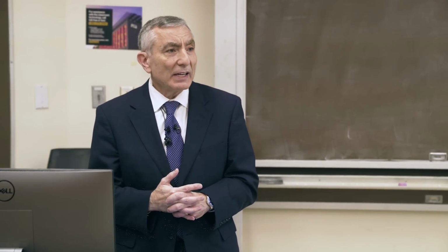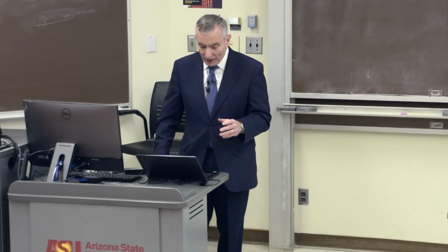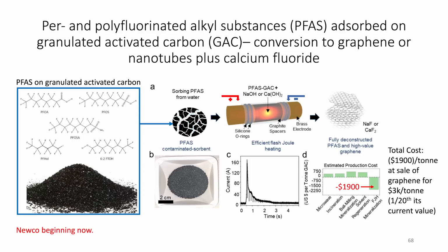You can get PFAS out of water fairly well by using a carbon filter. Carbon works actually quite well. And you can remove the vast majority of these water-soluble PFAS compounds from water. So here's what the PFAS compounds look like. You use activated carbon. So what do you do with the activated carbon now that it has PFAS on it? That is currently incinerated. There's a cost to that. Well, what we do is we add calcium hydroxide to it, or sodium hydroxide, and we flash it. All of that carbon turns into graphene, and the fluorine turns into calcium fluoride.